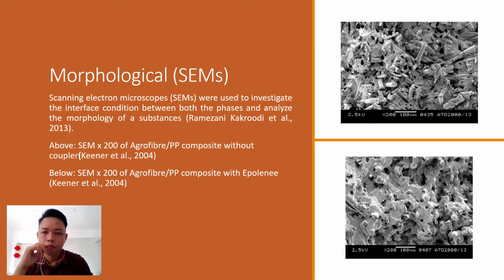For morphology, scanning electron microscopy is used to investigate the interface condition between the phases and analyze the topography of the substrate. In this study, I am going to use this to scan the specimen to see their interface. The figure above shows agrofiber and PP composite without coupler, and the figure below shows agrofiber plus PP composite with coupling agent. Same as in my study, it will show which specimen has less void, and I can also differentiate the percentage of MAPP by seeing the interface of every different specimen.